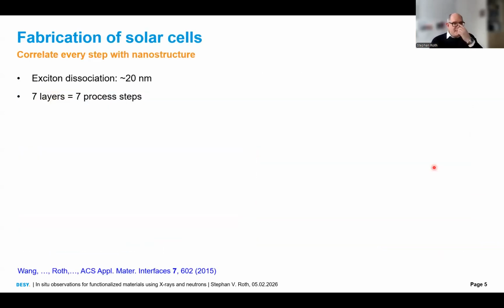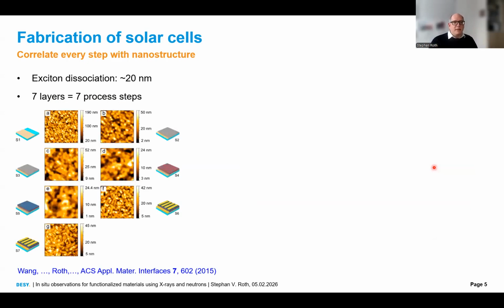And just to give you an example, when you fabricate a solar cell, we want to correlate every step with a nanostructure. Typically, these organic solar cells have 7 layers, meaning 7 process steps, not 7 different technologies, but typically you have spin or spray coating, slot die coating for the polymer layer. You can have liquid deposition for the silver nanowire layer. I will show an example. You can have physical vapor deposition for the electrodes or for the oxide layer. And what you first do, of course, is you use an AFM to look into the structure, but it's always the topmost layer you see.